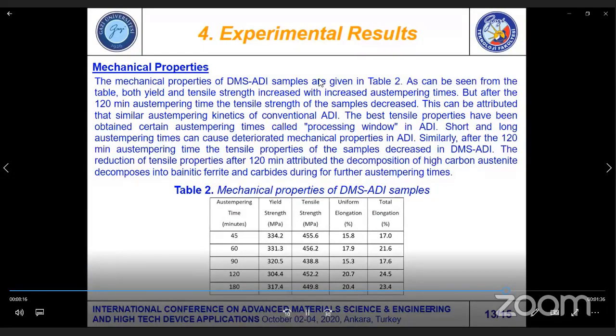Mechanical properties. The mechanical properties of dual matrix structure austempered ductile iron samples are given in Table 2. As can be seen from the table, both yield and tensile strength increased with increased austempering times. But after the 120 minutes austempering time, the tensile strength of the samples decreased. This can be attributed to the similar austempering kinetics of conventional austempered ductile iron. The best tensile properties are obtained at certain austempering times, called the processing window in austempered ductile irons. Short and long austempering times can cause deteriorated mechanical properties in austempered ductile iron.